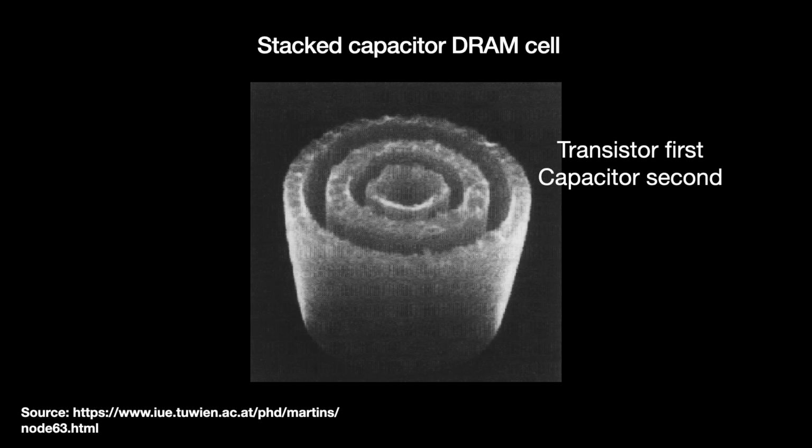While trench capacitors gained traction early on, stacked capacitors became more widely used after the capacitors adopted high-K metal dielectrics to retain high capacitance. Since these dielectrics are heat-sensitive, we must do transistor first, capacitor second. So, stacked it is. Two recent major technology transitions for the DRAM industry have been EUV and the 4F² cell.